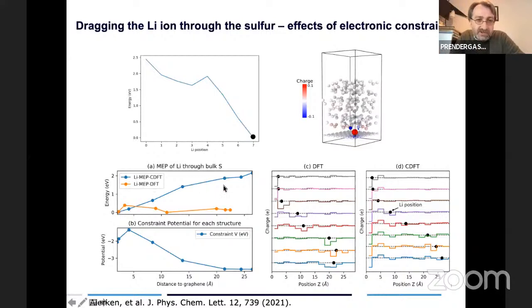However, if I constrain the charge to remain in the graphene, you see the expected behavior, right? There should be a gain in energy or a lowering of energy of the system as you bring a charged object to the graphene. And that's what you'd expect from electrostatics as well.